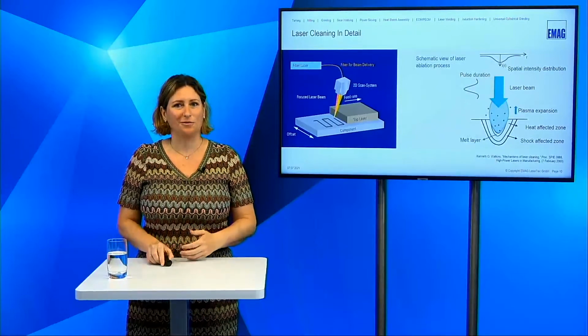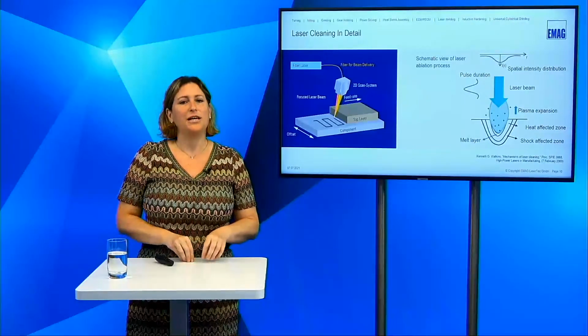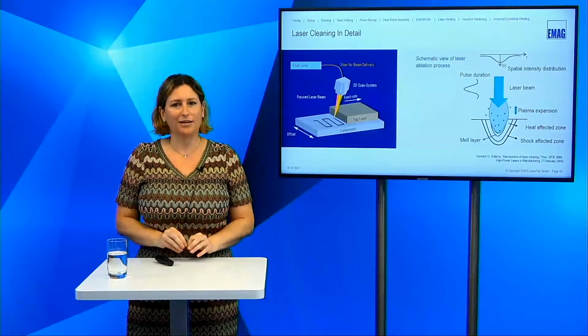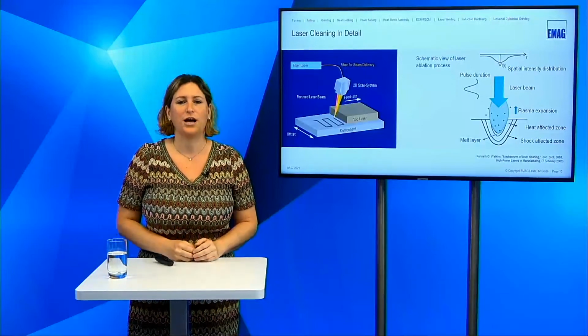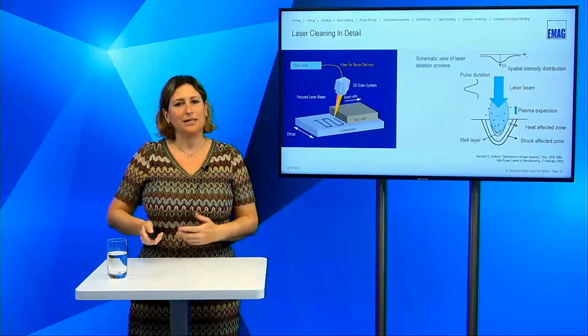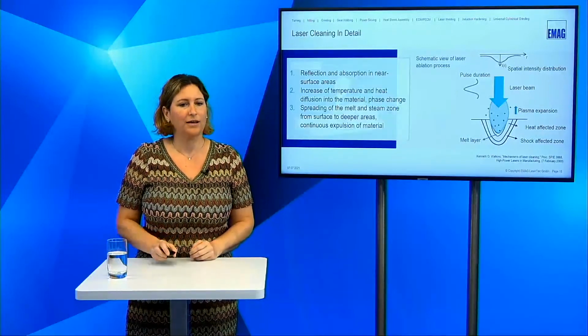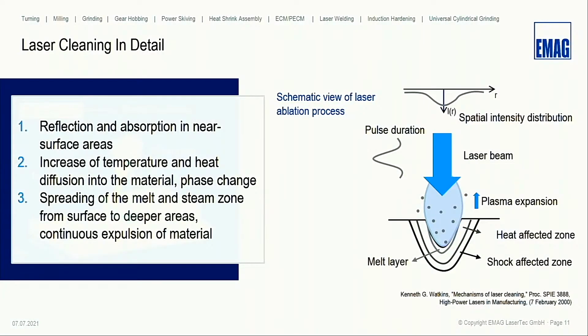Let's have a closer look into the interaction zone between laser beam and sample. It looks a little bit complicated. You have a lot of different zones which are happening during the laser process, but it's not as complicated as it looks. If we go through it in detail, we have the laser beam hitting the surface. The laser beam will be partly transmitted, partly reflected, and partly absorbed by the material. The absorbed part of the laser beam will increase the temperature of the material. And with more interaction time, the temperature will rise. You get a melting of the material, and later on also vaporization. So you remove the material away from the surface.